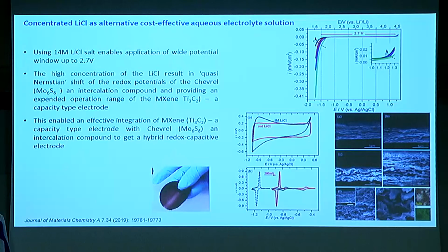We also tried to test this electrolyte in a molybdenum sulfide anode. And what you can see here is that in 1 molar, only this peak can be obtained, while the second peak cannot be obtained because of the hydrogen generation, and this is why it appears in a dashed line. And in contrast, when we use 14 molar of lithium chloride, we got a significant shifting of the redox peak. You see 280 millivolt, and then also the second intercalation peak can be achieved without any water splitting.